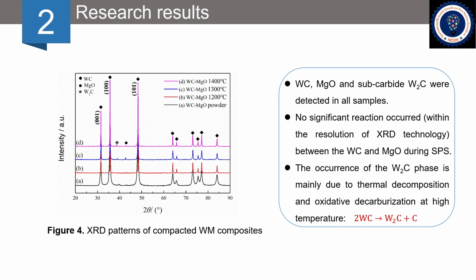There was no peak of impurity phase, indicating that no significant reaction occurred between the tungsten carbide and magnesium oxide during SPS. It was observed that tungsten carbide is the dominant phase in all the XRD diffractions. Meanwhile, it can be found that the amount of the W2C phase in WM composites increases with the increase of temperature.